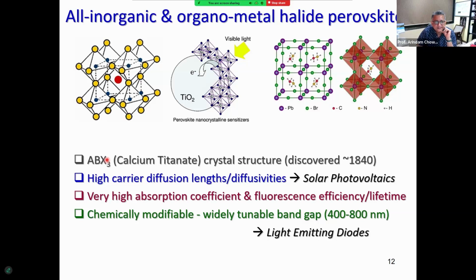And this is an example of all inorganic perovskites on the left. This is, for example, cesium lead bromide. You can also replace the cation cesium with an organic group, and you can have, for instance, methyl ammonium lead bromide, the structure of which is shown here on the right. It can be bromide, it can be chloride, it can be iodide. So you can change the halide groups in these materials, and you can end up getting different colors.